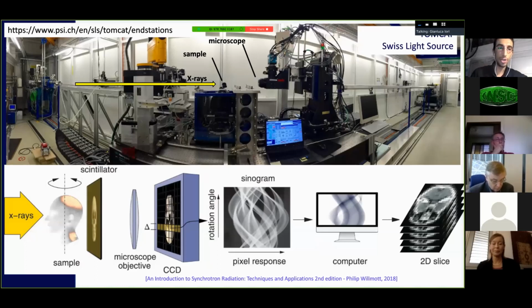The projection image is taken at different angles of the sample, and this is a sinogram, which is the pixel response of the detector for a single line through the object for all angles of rotation. After which there is a computer phase where the Radon transform is performed, and the tomographic reconstruction is computed. And this allows us to go from sinograms like this one to a stack of 2D slices, and therefore to a 3D volume of the sample.